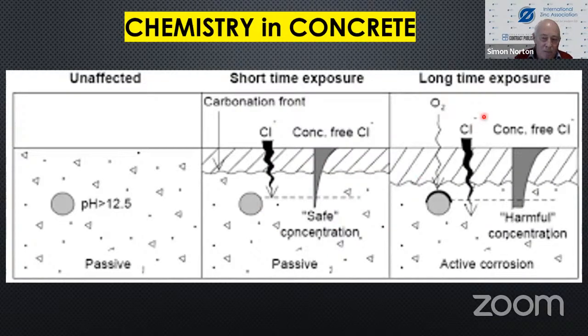But over a longer period of time, there's more concentration of chlorides, more oxygen reaches the center, more CO2, and you start to have an active corrosion cell. That's where zinc comes into play. And with zinc chemistry, if you take your rebar and you galvanize it before you put it into concrete, you will then have a much longer life out of your rebar. Just a short revision.